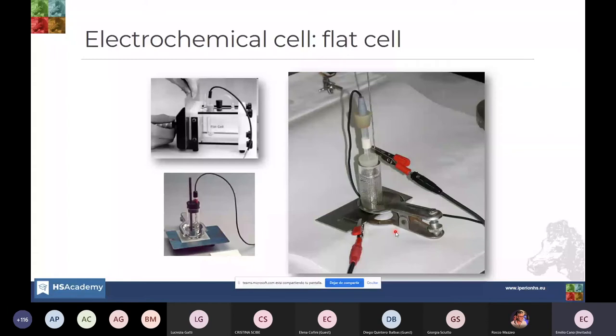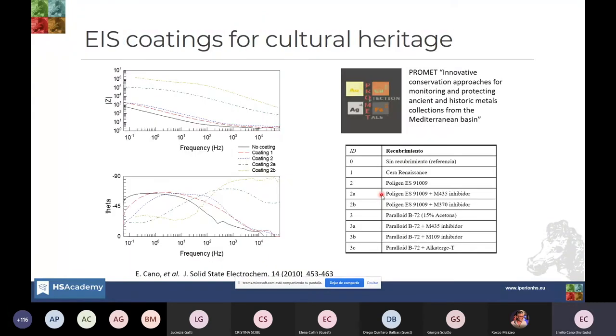On the right here, you can see the arrangement we used in our lab for a project some time ago. This is the sheet of steel that has been coated, which we wanted to test, and the reference and the counter electrode. And using this setup, within a European project, PROMET, we tested different coatings for metals. You can see on the left the Bode diagram. In this case, we have separated the phase angle and the modulus of the impedance. And just looking at a very simple interpretation, you can see here that the values of the modulus at these intermediate frequencies are very different for the different coatings.